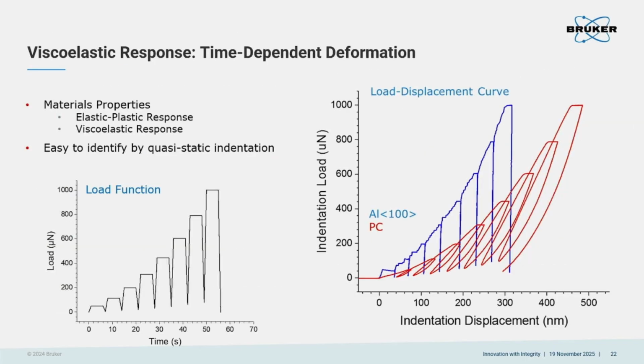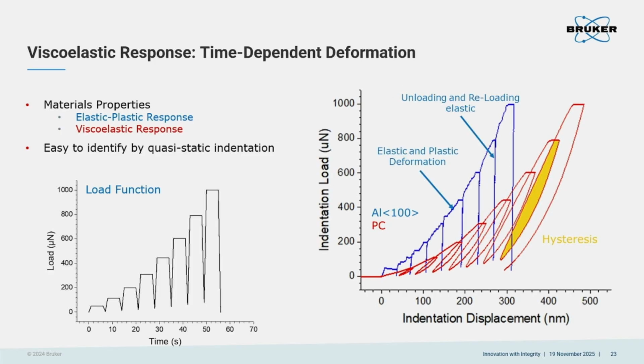Okay, so another viewpoint from which we can see this effect of rate sensitivity is the partial unloading method. The load function will be something like this. We use different cycles to get the loading, holding, unloading, and then do it again and again. The very interesting observation is if you take a look at the unloading segment together with the next reloading segment for the next cycle, you can see there are two different material responses. The blue dots are coming from pure aluminum, which is not so rate sensitive at room temperature. And the other one is a very typical polymer, polycarbonate, shown here.